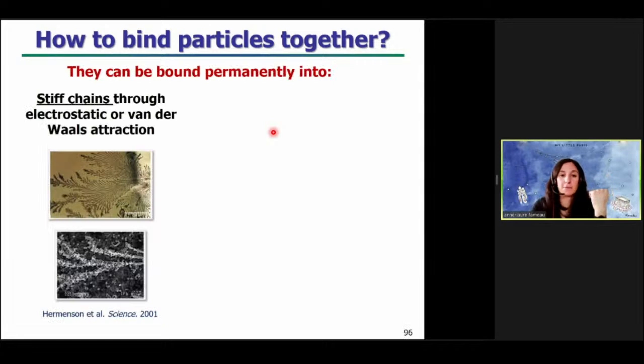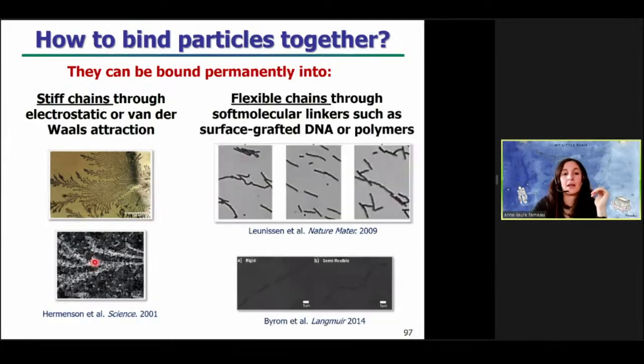So nanoparticles can be bound permanently together into stiff chains, and not flexible chains, through electrostatic or van der Waals attraction. As you can see here, it's nanoparticles under an electric field. You can obtain flexible chains, but you need to use micron-scale particles, so not nanoparticles, and through soft molecular linkers, such as surface-grafted DNA or polymer, as you can see on these 2 examples. So you need synthetic chemistry method. So the main problem is that you have flexible chain, but based on micron-scale particles. In our case, we want to use nanoparticles.